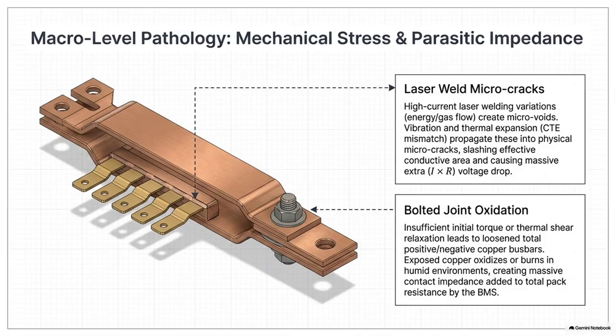But then you put this battery pack into a vehicle, and an automotive environment is essentially a continuous rolling earthquake. High cycle fatigue is the absolute enemy of a false weld. The vehicle is subjected to constant multi-axis vibration from the road, and simultaneously you have the thermal expansion mismatch we discussed. Right, because copper and aluminum expand differently when they get hot. Drastically different coefficients of thermal expansion, or CTE. As the battery heats up under heavy load and then cools down when it's parked in your driveway, the copper and aluminum expand and contract at different rates. They're fighting each other. Yes, and that induces massive shear stress precisely at that tiny, fragile weld joint.